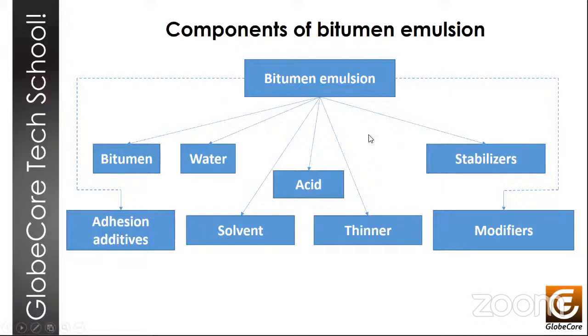Thinners, such as vacuum gas oils, oil fractions, etc., are added in a wide range, anywhere from 5 to 30% by weight, to increase the penetration of bitumen to the required value and to give the emulsion a stable liquid state. To improve the adhesive properties of the finished emulsion, we can add an adhesive additive.